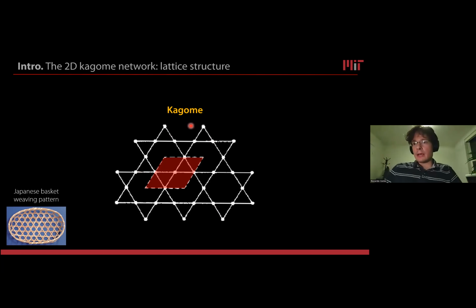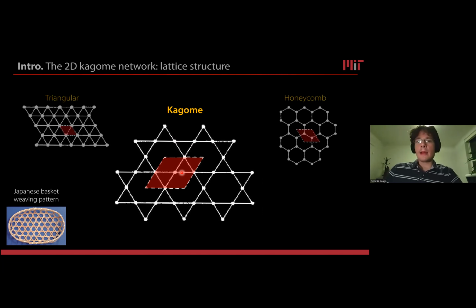So this is the Kagome network. The atoms are these small circles here. They occupy these sites on a unit cell which contains 3 sublattices, A, B, and C. So this is one sublattice in addition to the honeycomb system or graphene. But the Kagome shares a lot of common traits with both the triangular and the honeycomb lattice. In fact, it has the very same point group symmetries. And the only difference between these 3 lattices is the number of atoms in the basis set of the unit cell. So the triangular lattice only has 1 sublattice, the honeycomb has A and B, and Kagome has A, B, and C.